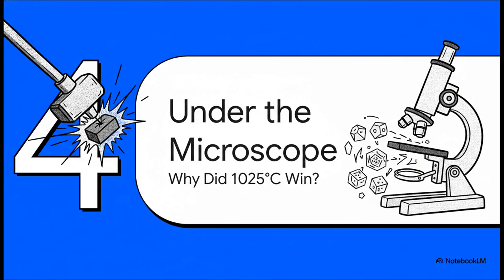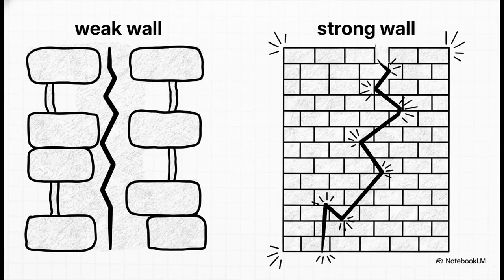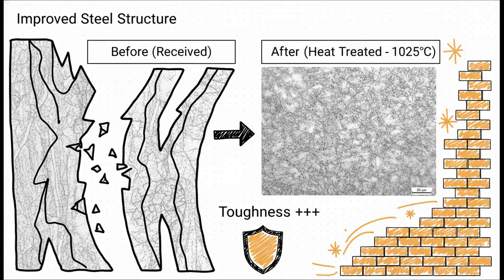To figure that out, the researchers had to go from that big impact test down into the tiny, microscopic world inside the steel itself. You see, a core principle in metallurgy is that a finer internal structure, what they call grain size, is usually a lot better. Just think of it like a brick wall. A wall made of small, tightly packed bricks is way stronger and harder to crack than a wall made of just a few giant, clunky blocks. A crack has to keep changing direction at every single grain boundary, and that just eats up energy and stops it in its tracks.